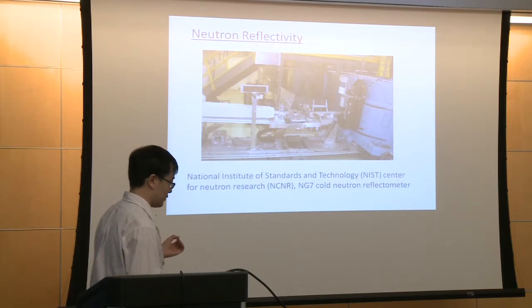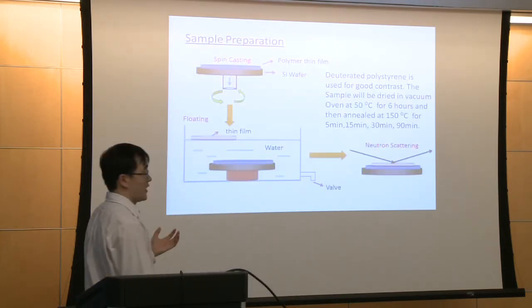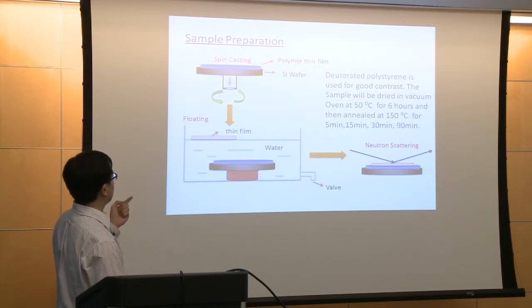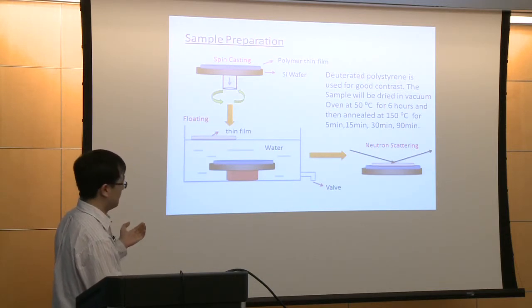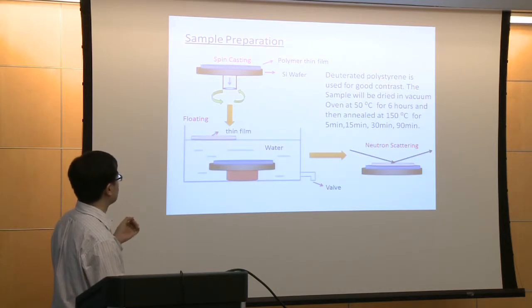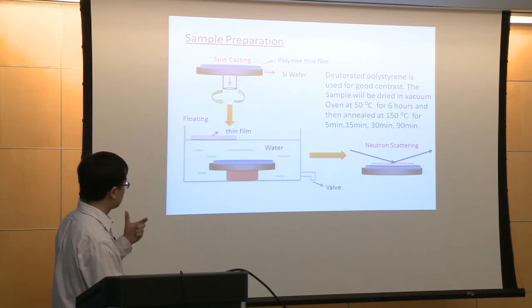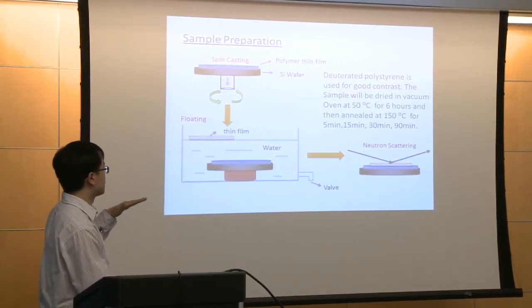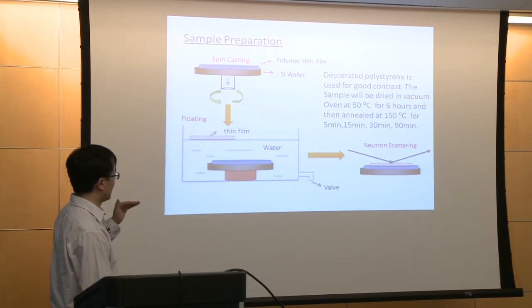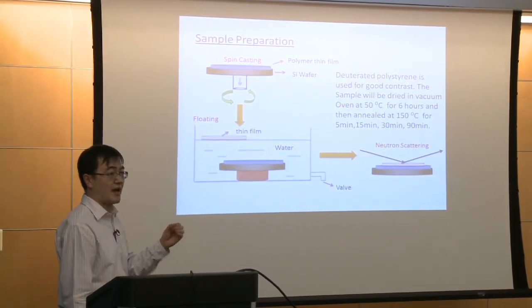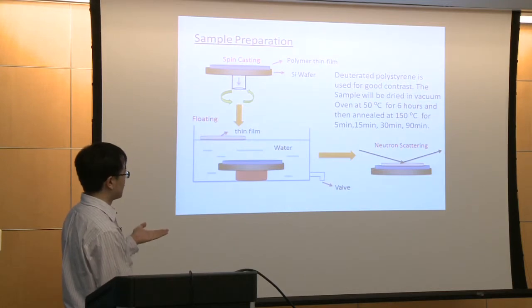It's called neutron reflectometer. So we prepare the sample like this. We first spin cast a very thin film, like 40 nanometer thick, on the surface of the silicon wafer. And then we immerse the silicon wafer into the water, and we float another layer on top, on the surface of the water. Then we try to empty the water, so the thin film will be deposited onto the surface of the silicon. In this way, we can fabricate a bilayer on the surface of the silicon wafer.